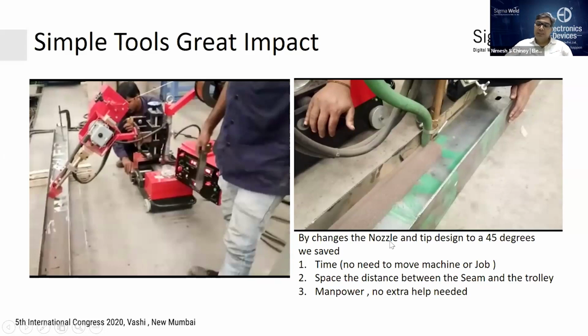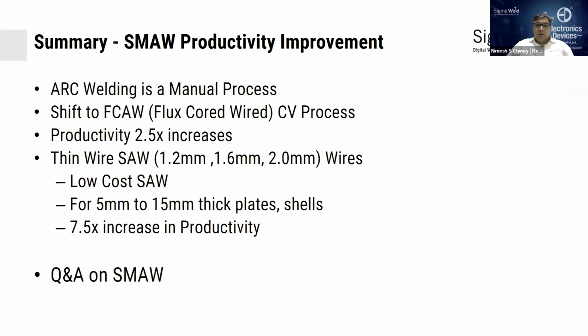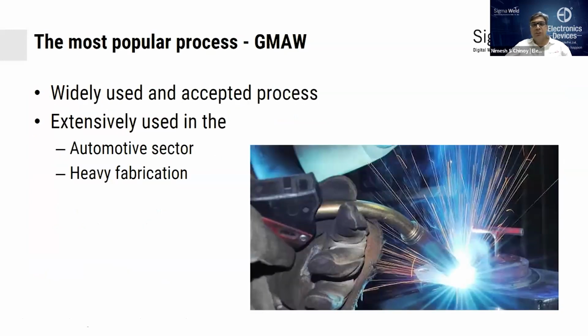So the space saving is there, time saving is there, and no extra help required. Productivity improves. So in summary, from arc welding, we can move to flux core, which is a constant voltage process to improve the productivity 2.5 times, or to thin wire submerged arc, which can help you increase the productivity to almost 7.5 times. Quickly diving into GMAW processes,